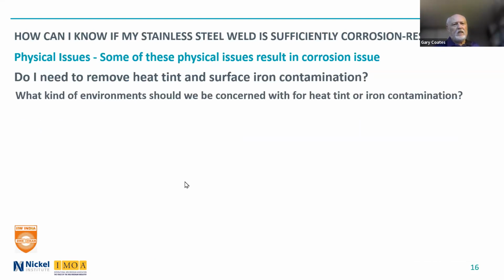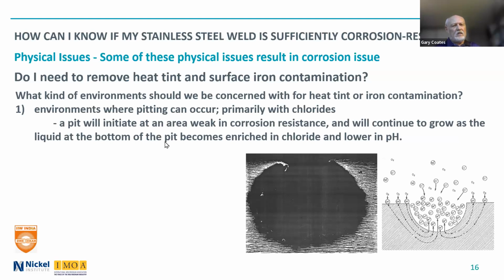Do I need to remove heat tint and surface iron contamination? Well, first of all, let's look at what kind of environments we should be concerned with. And generally, those are, to start with, environments where pitting can occur, and that's primarily where you have chlorides. Theoretically, if there are iodides or bromides present, that is also possible. And a pit will initiate in a weak area, for example, iron contamination or the heat tint, and it will continue to grow, as the schematic on the right-hand side shows, that the chloride becomes enriched in the bottom of the pit, and it also has a lower pH. So the environment at the bottom of the pit is much more corrosive than the bulk environment in the solution there.